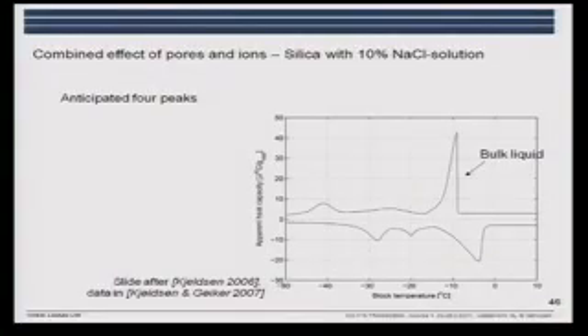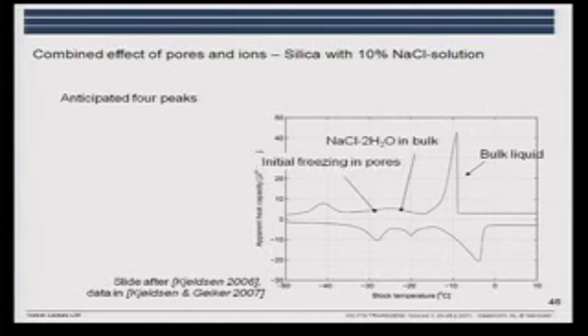If then we have a system where we have pores and ions, we have the bulk liquid freezing, we have the sodium chloride in the bulk, and we have initial freezing in the pores, and we have the salt in the pores. And then you can imagine, this is just one pore size. Then we have the system, our cementitious material, where we have a variation in pore sizes, and we have several different ions in solution, and the concentration changes. And we don't have a phase diagram for the pore liquid.